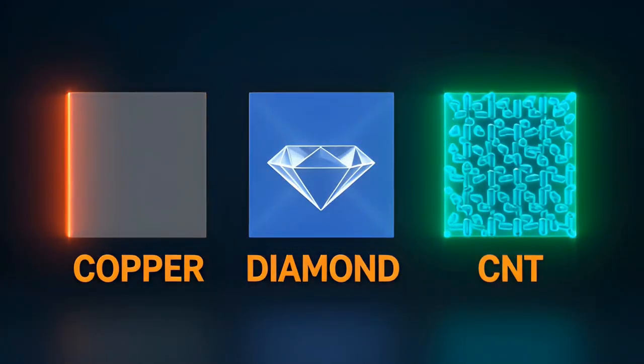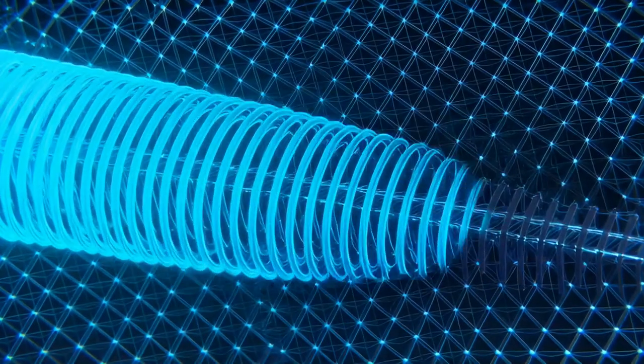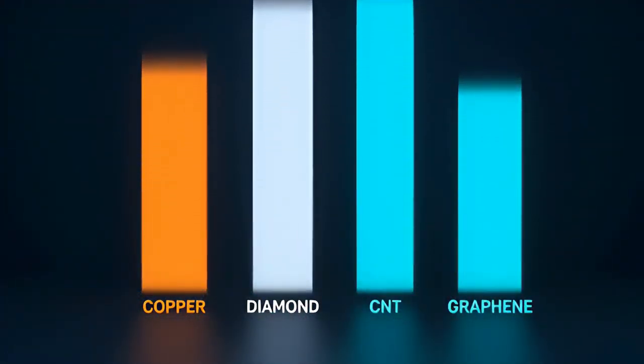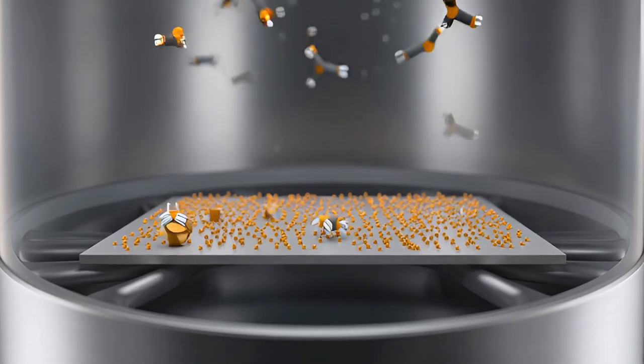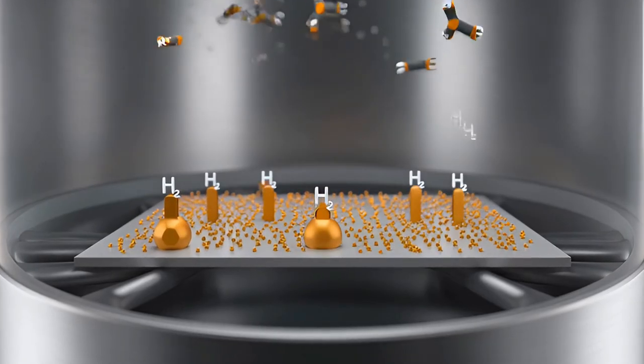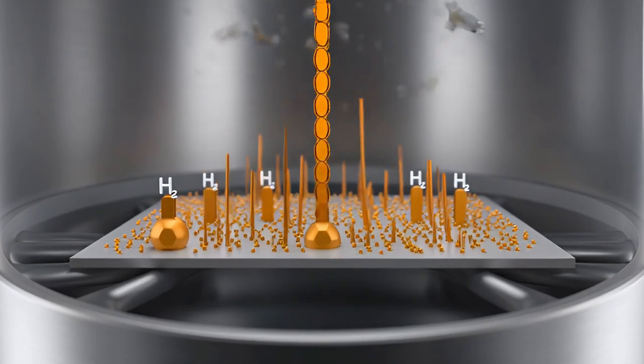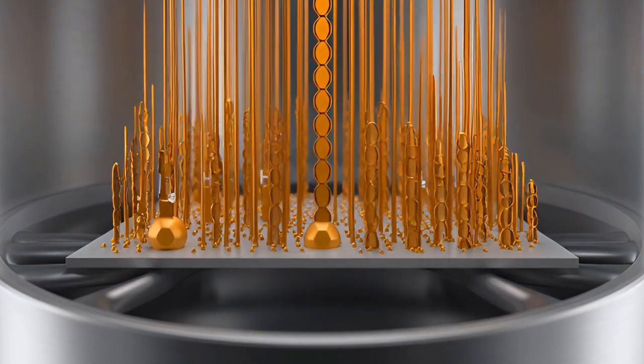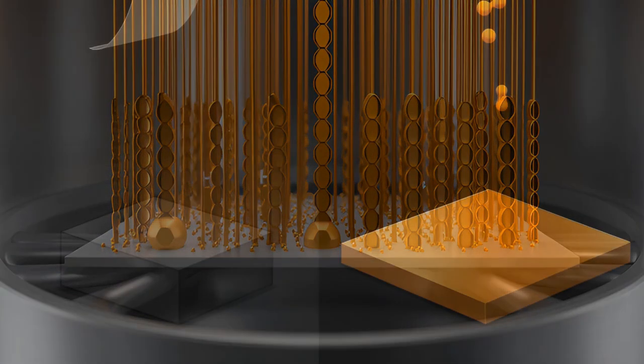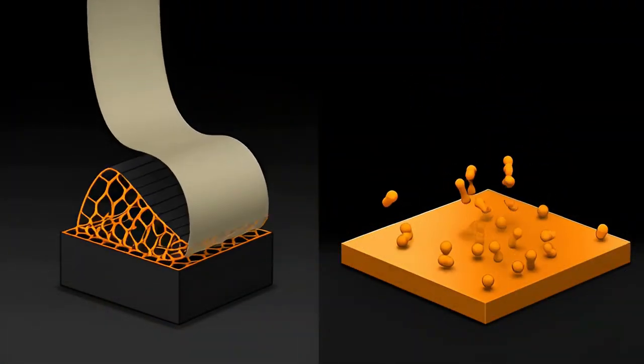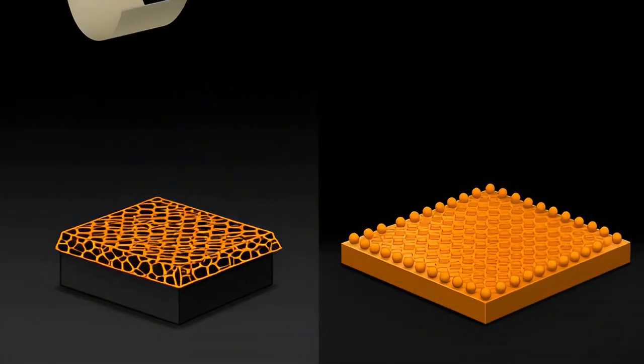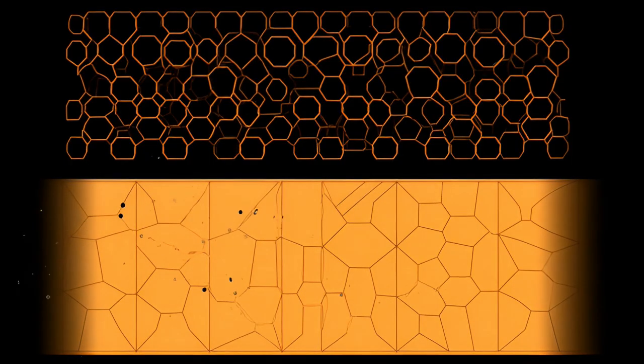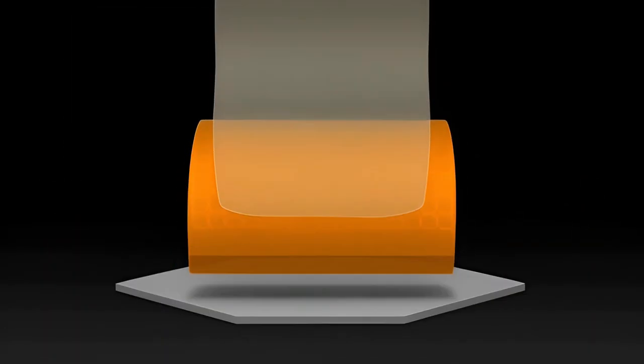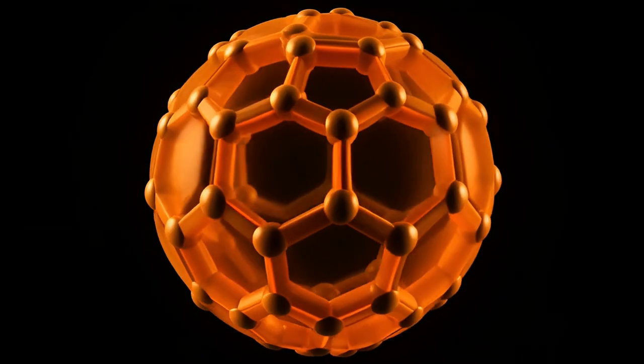Not only that, but carbon nanotubes conduct heat 15 times better than copper. To make them, we grow nanotubes from catalyst nanoparticles in hot hydrocarbon gas, where they assemble atom by atom. But there's a manufacturing trade-off. Exfoliation gives perfect graphene sheets, CVD gives industrial scale, but no single method gives both at once.